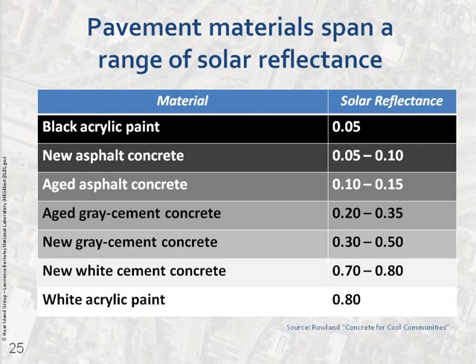The exact opposite happens when we look at cement concrete. When it's new, it's more reflective because it's, of course, lighter. And as it ages and soils with tire tread and oil, it actually darkens down to about 20 to 35%. And you'll find that a lot of these are ranges because things soil and age differently. Also, not all cement is created equally, and variations in mix come out with variations in solar reflectance.